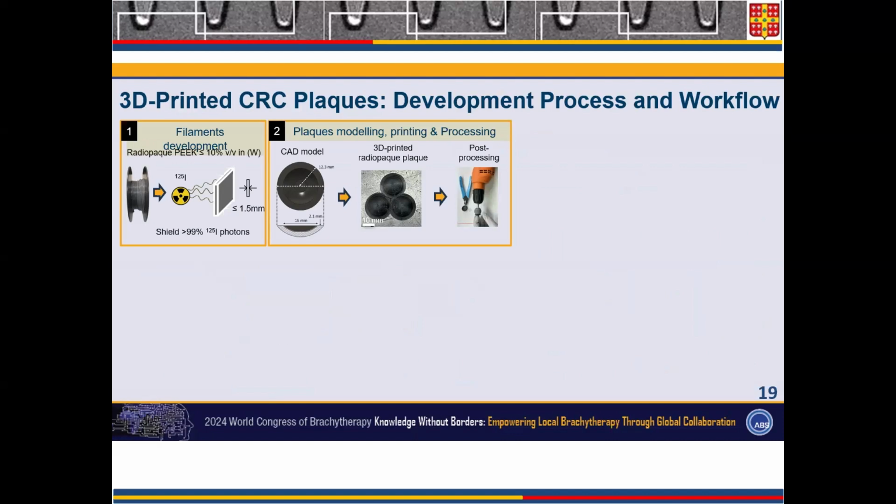Tungsten is relatively biocompatible. It is encapsulated by the polymer. We expect that it will not leach that many tungsten ions, which are not necessarily very toxic. So this is a toxicity that can be controlled pretty well. And there are other metals that we can blend into these polymers. So we developed these filaments with a very high content of metal. They were assessed by CT imaging and different types of modalities to demonstrate that they really do block the photons that are used